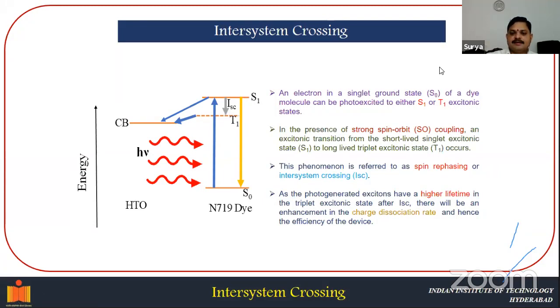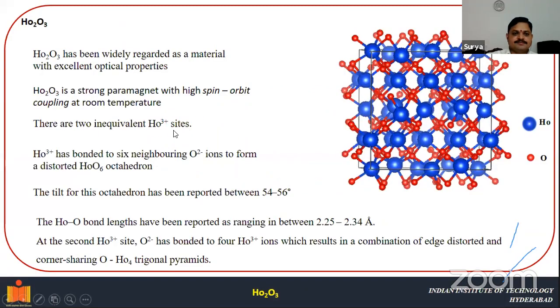All these things will happen if you have a strong spin orbit coupling element. This spin orbit coupling will unlock the transition between the singlet excitonic state and the triplet excitonic state. For this reason, we have used holmium oxide for our purpose. Holmium oxide is widely regarded as a material with excellent optical properties. It can absorb more light, and it is also a very strong paramagnetic material. It also has a very strong spin orbit coupling.